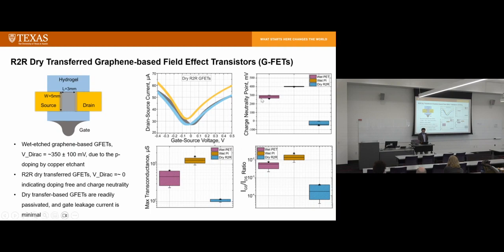To summarize the results we have over here. This is wet transferred graphene on PET, and this sample is wet transferred graphene on polyimide. Both of them have high V direct, so this shows charge neutrality is not good, and our samples are close to 0, so it's very good charge neutrality. This is very important for following processes when people want to use graphene to build sensors and field effect transistors.